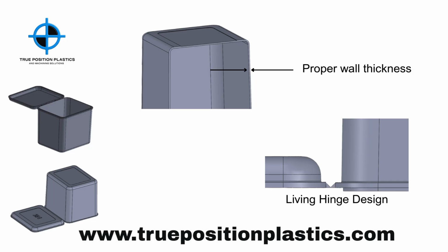And when we talk about those thick to thin transitions in cooling, there's some interesting physics going on there that directly impacts the final part, isn't there? You mentioned sink marks and voids. There absolutely is. Think about it. In thick regions, the molten plastic simply stays hot longer, much longer. This directly translates to longer cycle times, which hits your production cost. It also significantly increases the risk of those sink marks or internal voids we talked about. And crucially, it creates uneven packing and shrinkage across the part. That's a major cause of warpage, where your part comes out bent or twisted instead of flat.